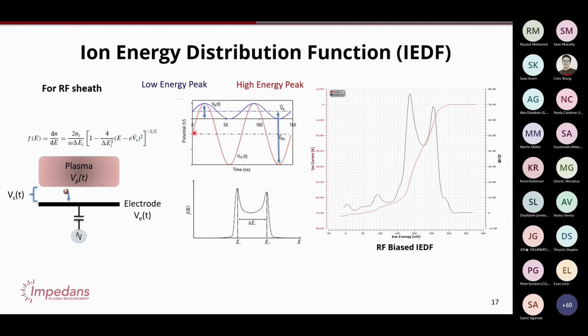What's happening is there are times when the voltage difference between the RF being applied and the plasma potential is quite low, and in those cases you're going to get low energy ions. And there are other times, when you're on the negative part of the RF cycle, you have a very large voltage difference, so that's going to produce higher energy ions, and then you have everything in between. So what ends up happening is you end up with this more complicated distribution.